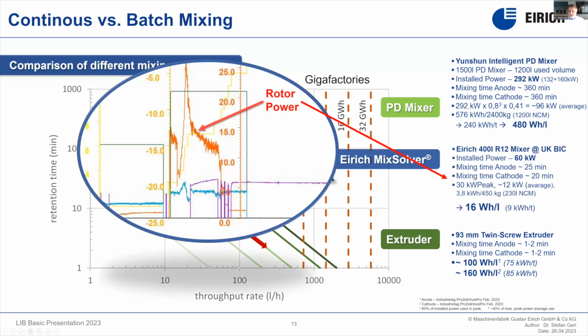With the Eirich mixer, you can go down even more. Even if we have big motors like 60 kilowatt for rotor and mixing chamber, we have just this very, very short peak where we need this extremely high motor power, and then we fall down again during the kneading phase. This means we have just an average of about 12 kilowatt, ending up with about 16 watt-hours per liter. This means we are saving, in comparison to the PD mixer, more than 90% of the energy.